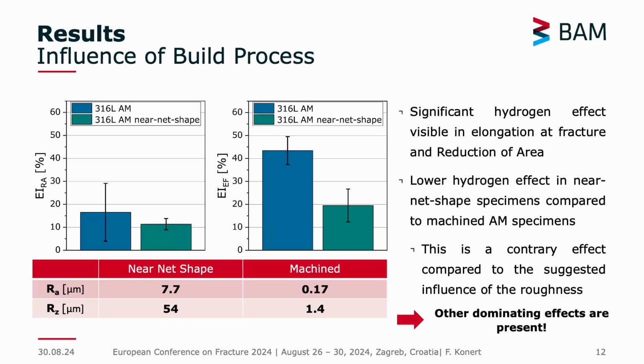course, out of the manufacturing process of the material itself, so the laser powder bed fusion process, you have some surface layers or another dominating effect which is present, but it's not yet clear whether that is time dependent or not. So we should go a little bit more in depth there, whether it is really an effect which is present over the whole lifetime of these additive manufactured components, if you manufacture components in this way.